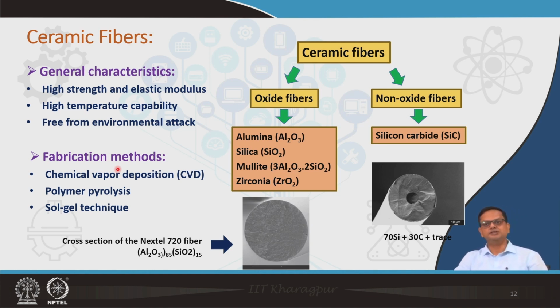The next one is polymer pyrolysis. Now, what is polymer pyrolysis? It means you need to think about a precursor which has high molecular weight. Obviously, this is a polymeric precursor with high molecular weight and long chains, and it should contain certain elements. For example, let us say I am trying to make silicon carbide fiber. That means it has to have silicon in it. It is a polymeric material containing silicon, and carbon is anyway there, and we have to do something so that this silicon and carbon get combined and we get silicon carbide, but we get rid of the rest of the elements by a pyrolysis technique, or high temperature synthesis technique, which is called polymer pyrolysis.